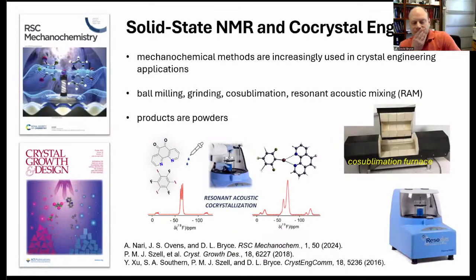Okay, so as mentioned, we're interested in these halogen bonds. There's been a lot of work on these types of co-crystals done over the years with solution chemistry and also with ball milling. So we thought, well, can we make these using RAM? Many of you know that RAM is a slightly different technology, where we're not bashing ball bearings into the powders, so perhaps a somewhat less harsh technique. But we nevertheless wanted to see, can we make halogen bonded co-crystals in this way, both dry and perhaps with a couple of drops of liquid added.